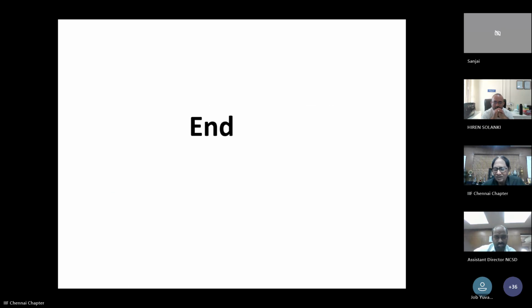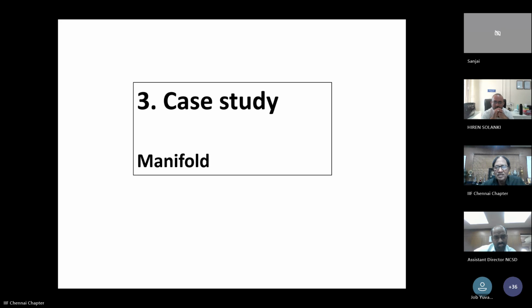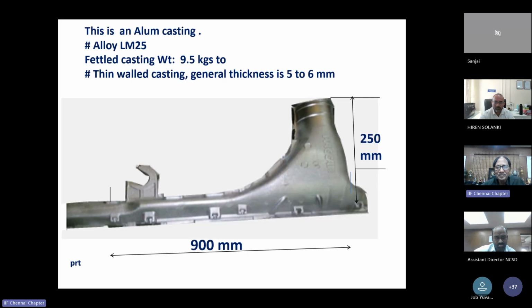The end. Now let me go for the third case study. Manifold. It's something different. This is a very long, thin casting. Hardly, the thickness is varying from 5 to 6 mm. Very, very long. This is about a meter long. The back side of it is hollow and formed by a core. The weight is 9.5 kg shot weight.